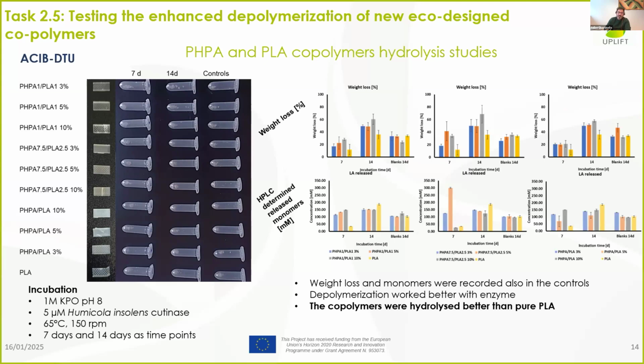And after the enzymatic approach with Humicola insolens cutinase, we defined which pattern of degradation we found, in terms of weight loss and HPLC. As I said before, PLA might be more recalcitrant to the enzymatic approach, but we found out that using 3% of PHPA, the enzymatic hydrolysis was enhanced. Which means that the eco-designed polymers were actually better in terms of degradation than the pure PLA.